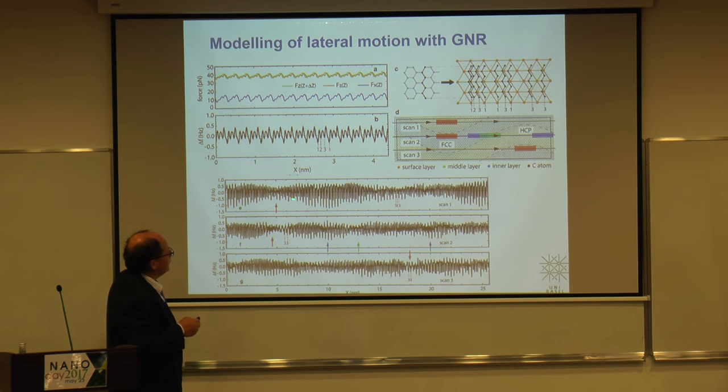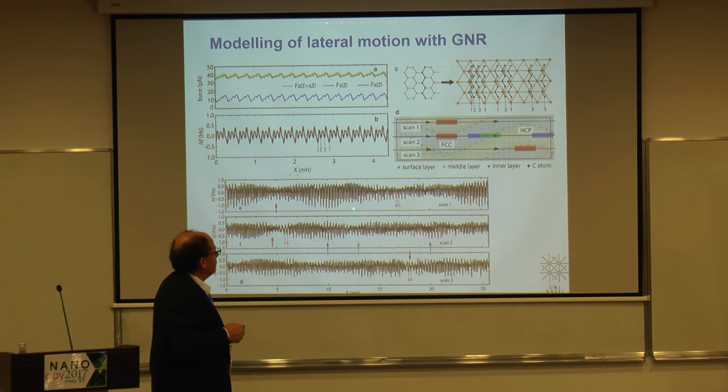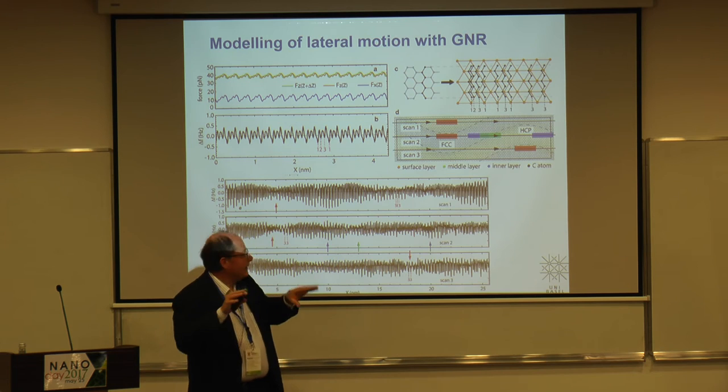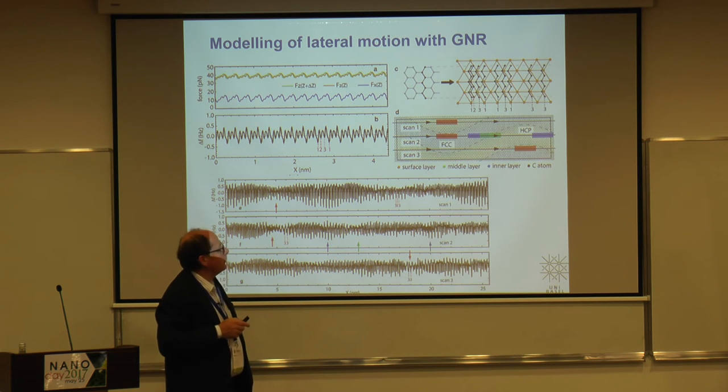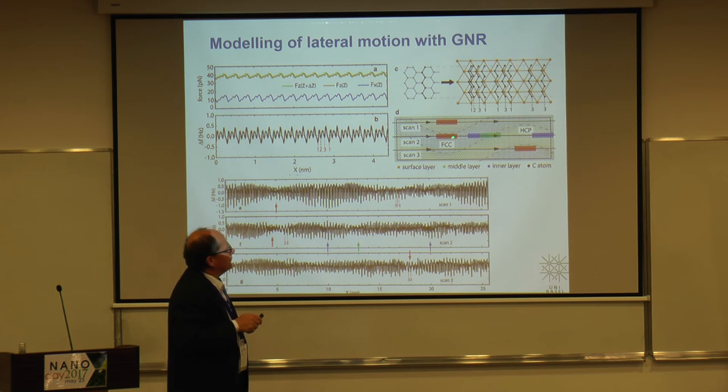And they find basically, you see here, this is also this envelope here. If you zoom in, you see this kind of typical periodic pattern, which has to do with the substrate. And so they find that this transition here, one has to say, the gold surface is reconstructed. So it has little valleys, very smooth mountains in a way. So it is FCC, face-centered cubic, and HCP areas, and so this is typical for this reconstruction on gold.